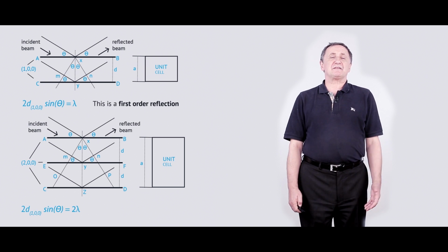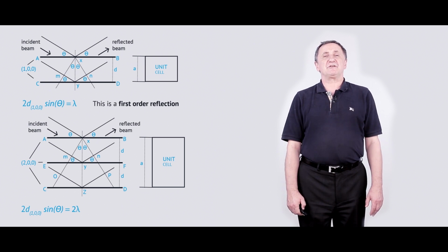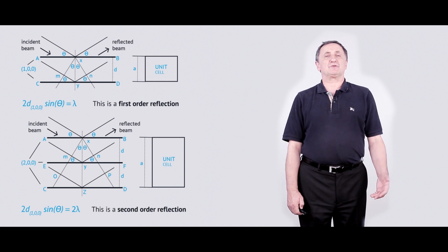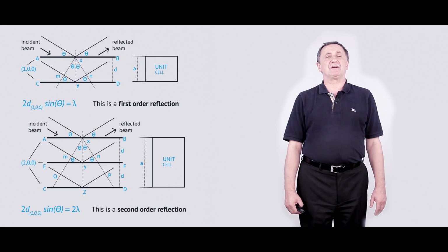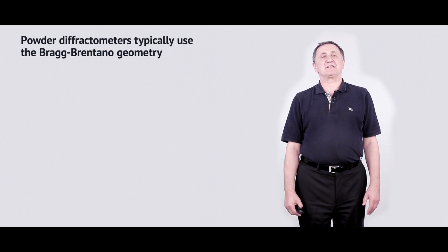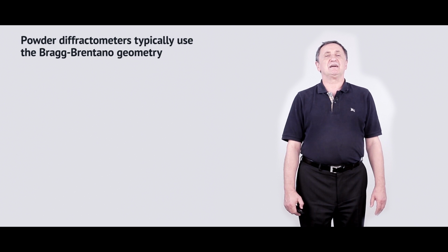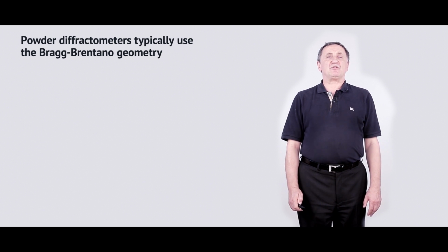And if so, then by measuring the interference picture, one can calculate d_hkl, and knowing d_hkl and assuming the type of the crystal structure, one can calculate the characteristics of the unit cell. That's the whole idea.